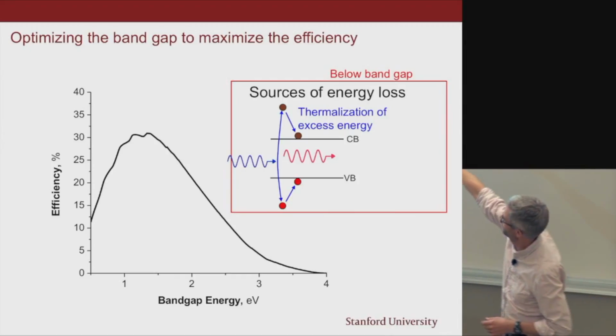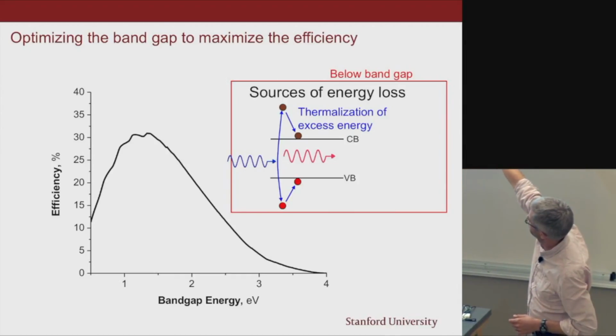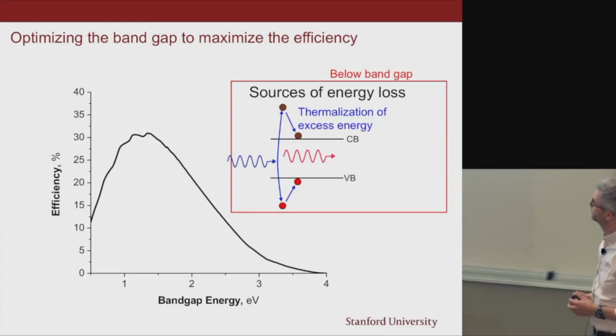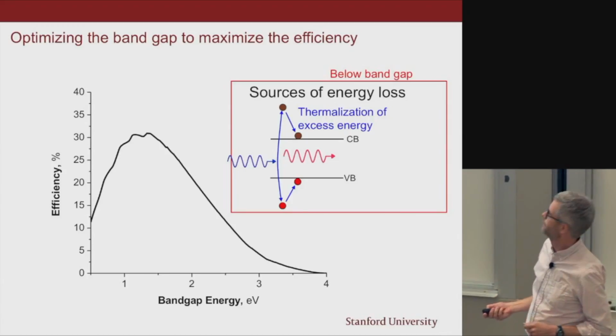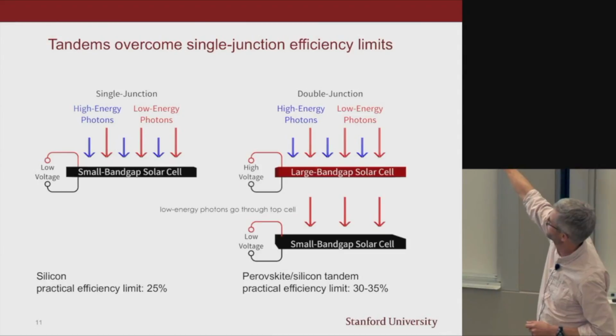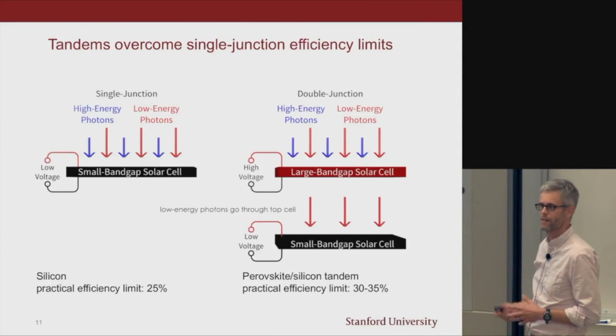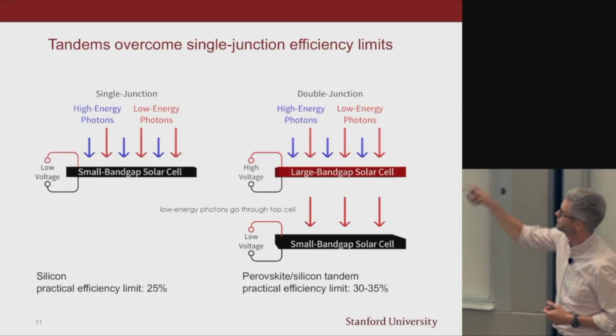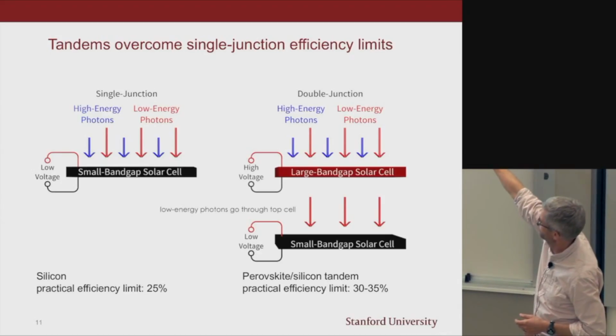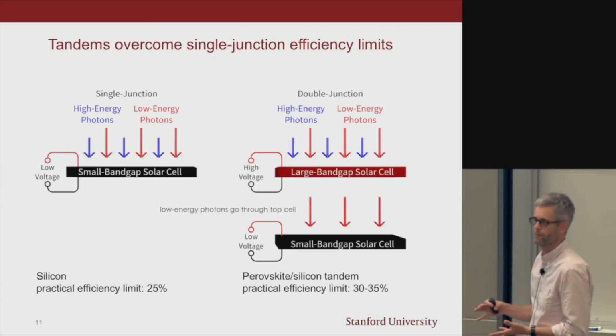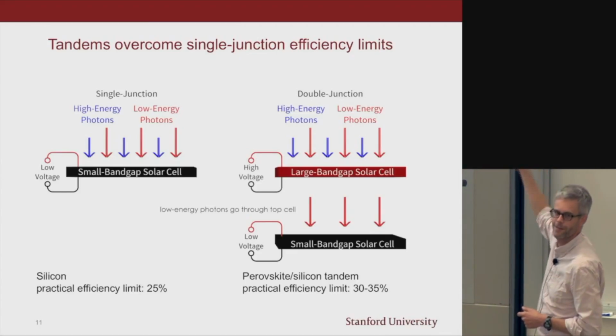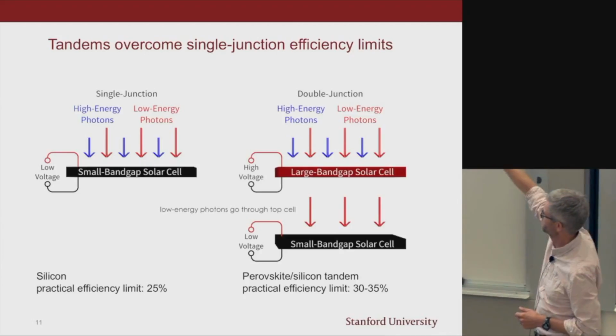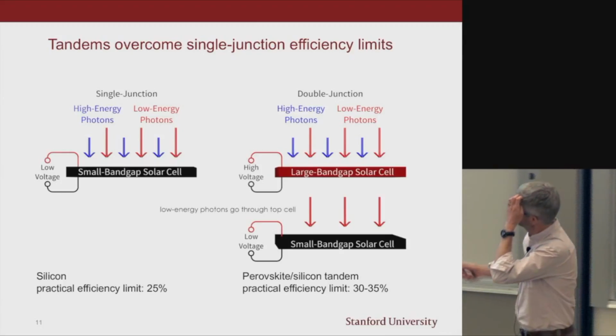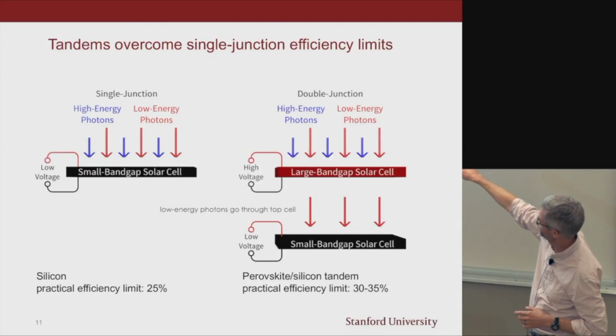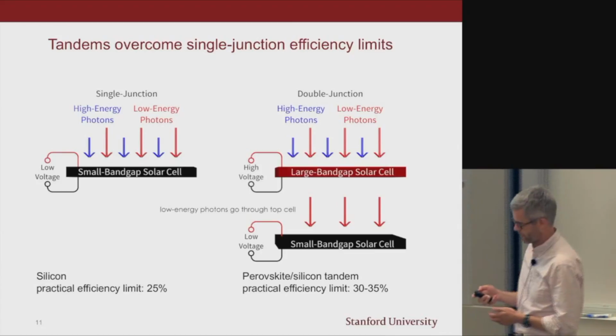When you look at the trade-off, you find the efficiency versus band gap looks like that. The ideal band gap is 1.4 electron volts, and you can only get about 33% efficiency. But that's with one semiconductor. The way to do better is to have two semiconductors and use one of them to harvest the high energy photons. That will have a higher band gap, and that cell can generate a higher voltage than silicon can. And then you can also have a lower gap cell to capture another part of the spectrum. You can do even better with 3 or 4 or 5. However, as you add layers, the cost will go up, and so I personally think 2 layers is ideal. I think that we can go from a practical limit of around 25 to something up in the range of 30 to 35 if we do this.